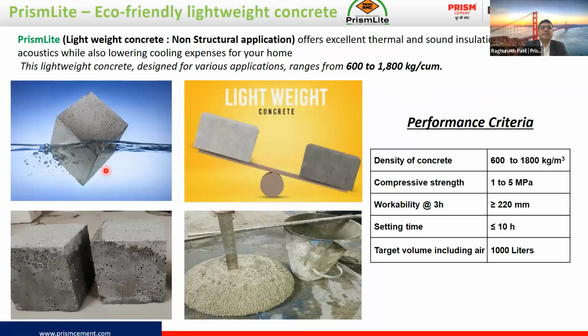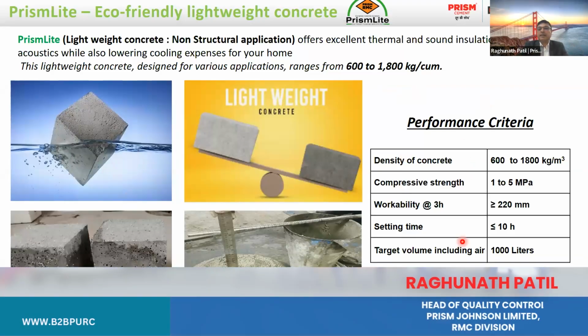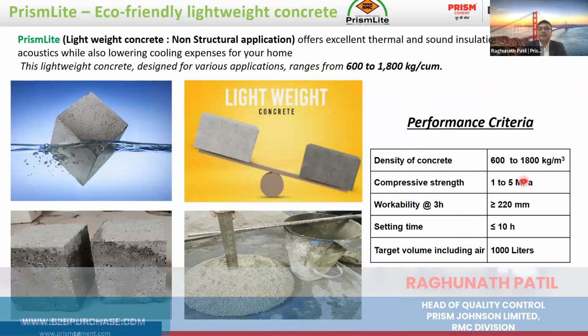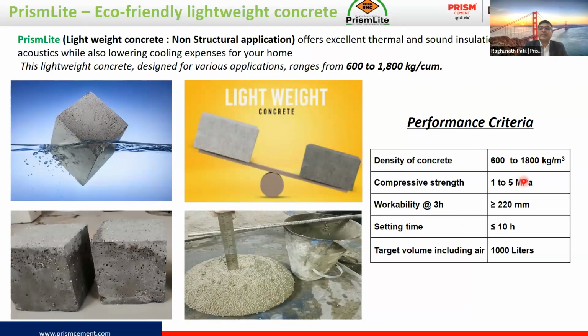Suppose if you see concrete density less than 1000, it floats over the water, because the water density is 1000 kg per meter cube. As for the performance of this lightweight concrete, the density of this product is 600 to 1800 kg per meter cube. Concrete strength is 1 to 5 MPa only. That's why we prefer this concrete only for non-structural applications.